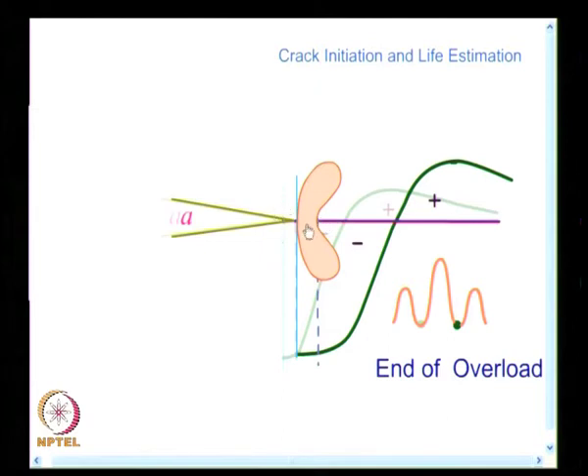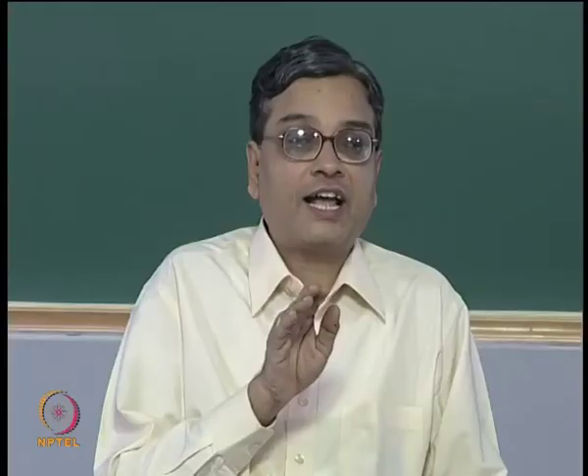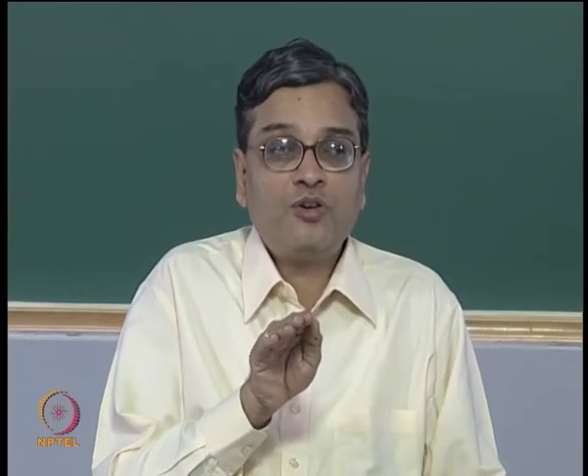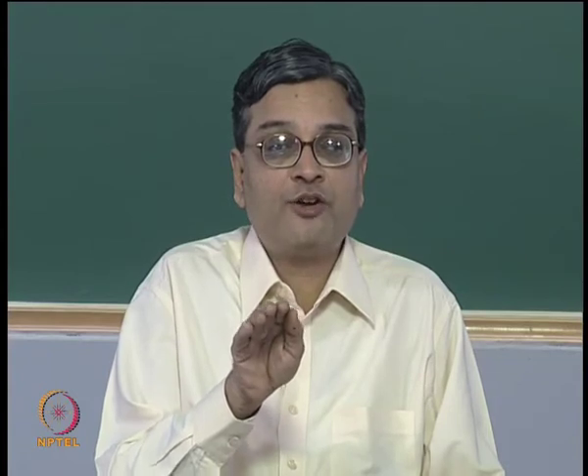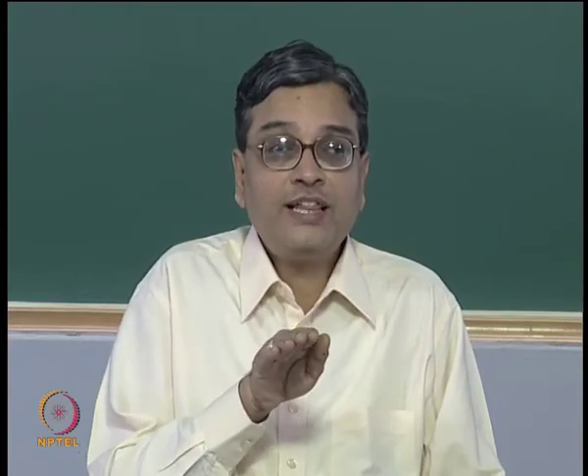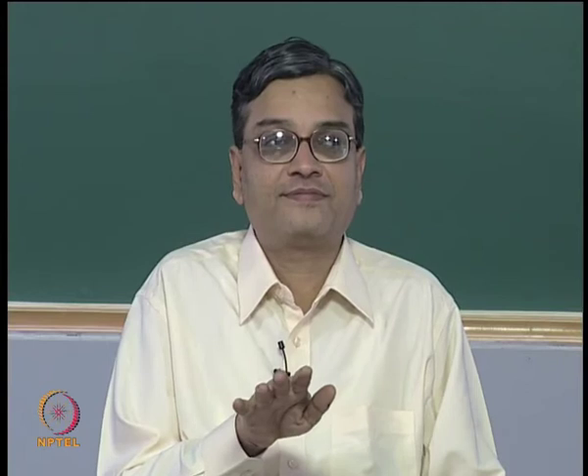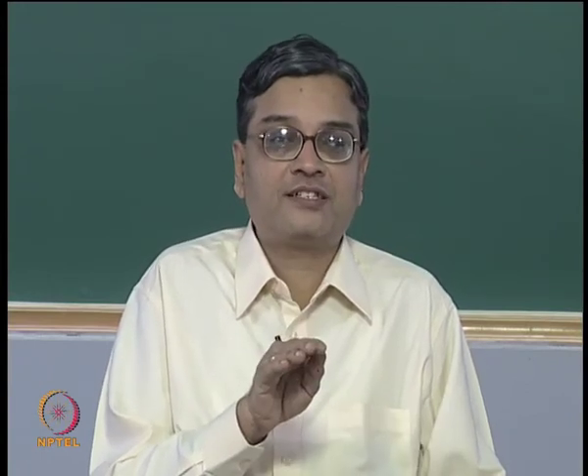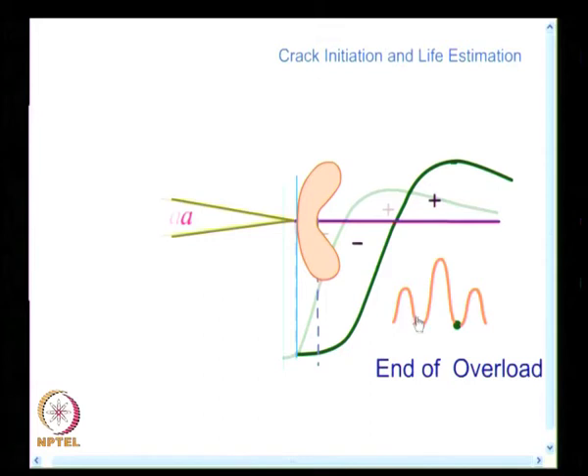Now, what you will have to realize is the crack has to come out of the larger plastic zone introduced by the overload. During that phase, the crack growth rate is retarded. That is the physics behind it. So, in order to appreciate this, you will have to recognize whenever you have loading and unloading, residual stresses get formed. In this case, what happens? I have a smaller load followed by a larger load. So, for a smaller load, you have a small sized plastic zone. For a bigger load, you have a larger plastic zone.